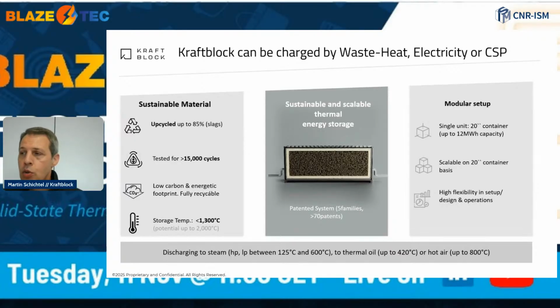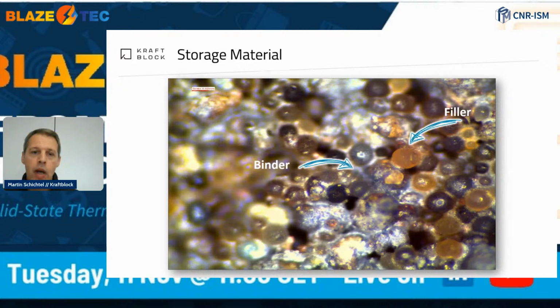Let's have a closer look at the storage material to describe why it's so special. Our storage material, as I explained, is a combination of what we call capacity fillers and a very special binder. The capacity fillers, like steel slag, we mill down to smaller than 200 microns in a very specified grain size mixture to get maximum density of the core material itself. Then we mix it with our special binder. The special binder is a phosphate. What is the idea behind it?